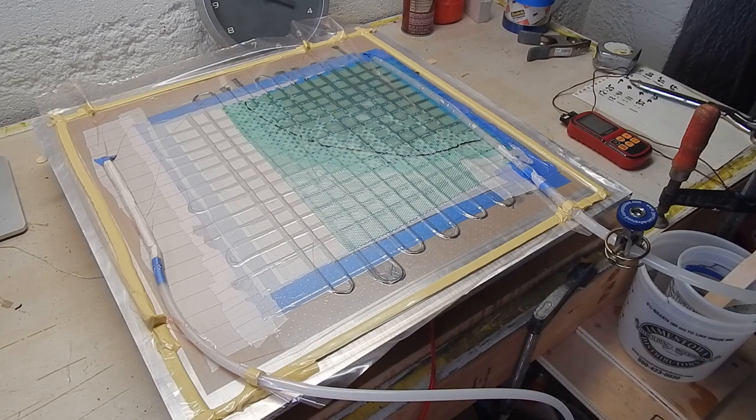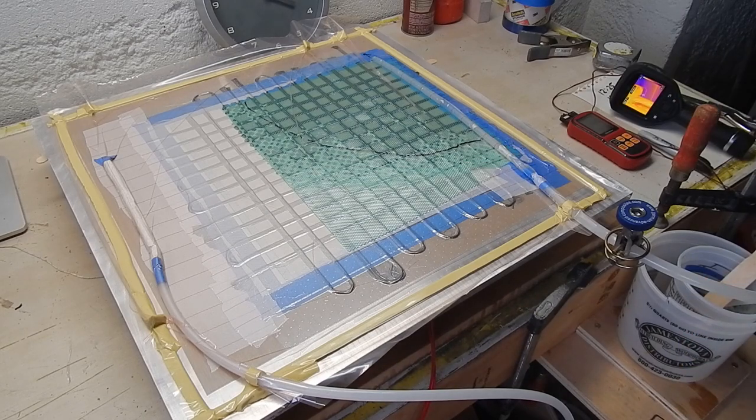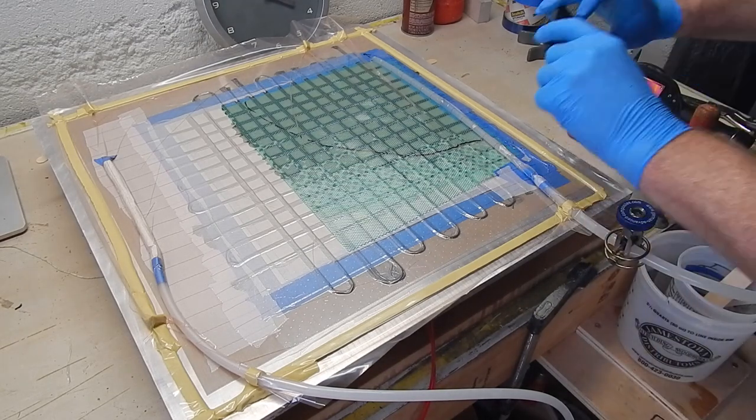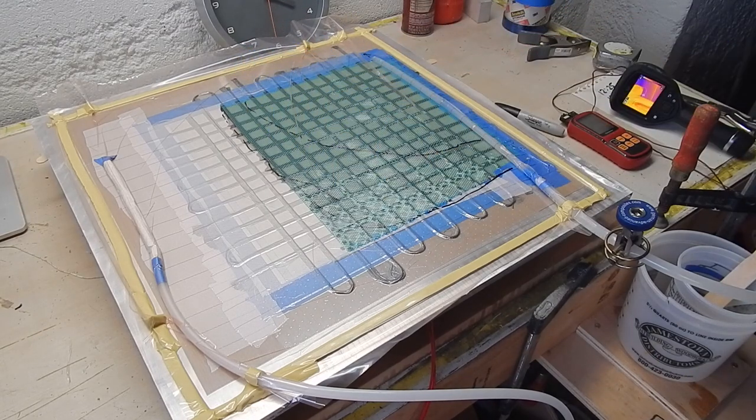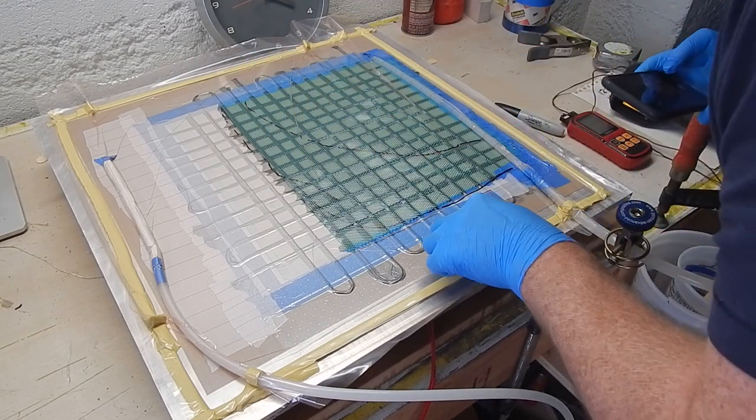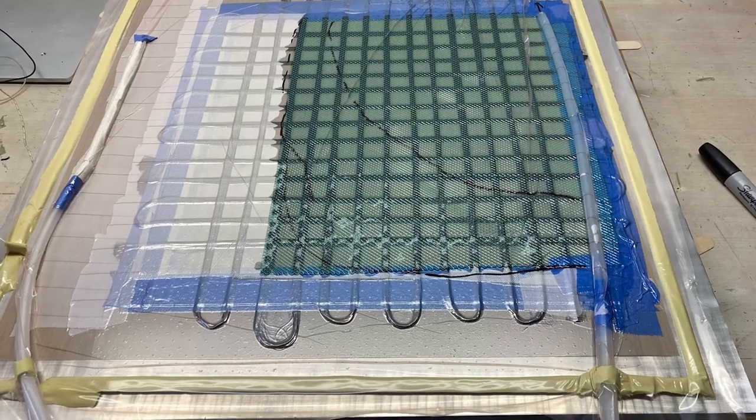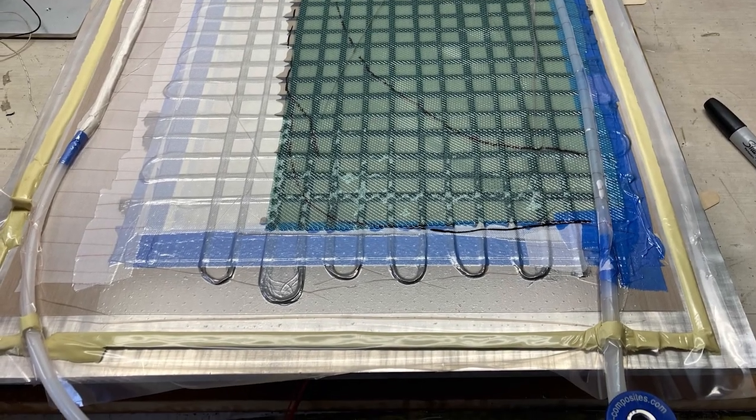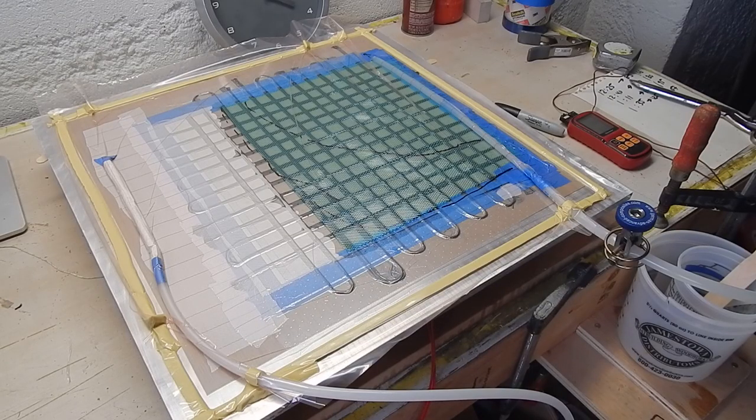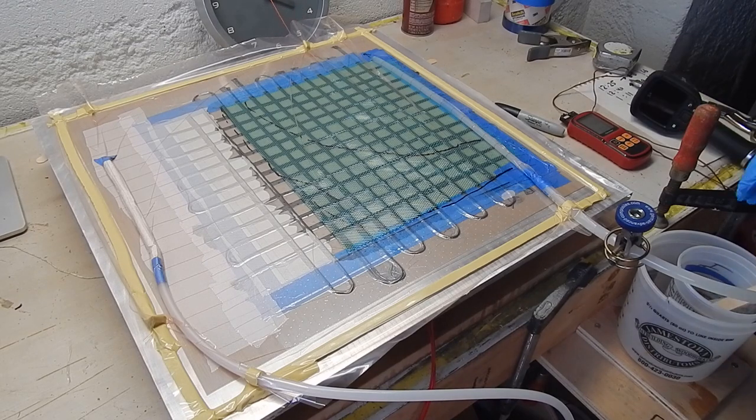I'm not sure why it's not coming out. The rest is a smaller diameter spiral wrap, but it's feeding fast enough with that flow media. This won't be a huge issue, but it's something to be mindful of. The resin will follow the easiest path, and if that easiest path is not where you want it to be, sometimes that can be a problem.